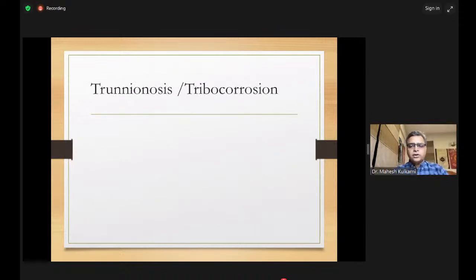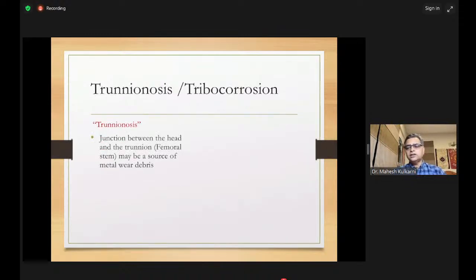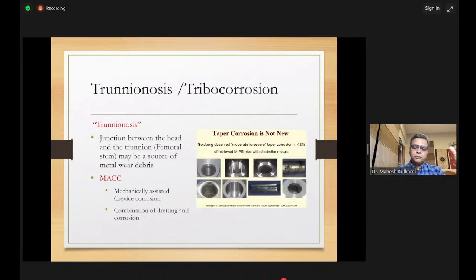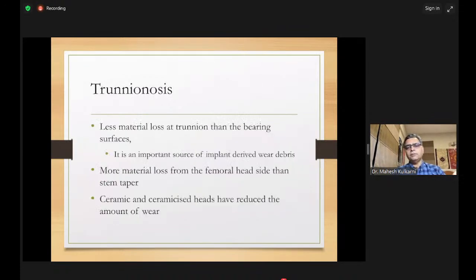We will touch upon trunnionosis. It's a large topic, but basically it's the junction between the stem taper and the female bore on the femoral head. That junction, which acts as a crevice, can lead to corrosion. It is a mechanically assisted crevice corrosion, and it will allow the metal to degrade away, and metal ions can be released, leading to toxicity and local damage like pseudotumor. The incidence is very low, but both ceramic and oxinium are inert materials, so they might be protective against trunnion problems in hip replacement.